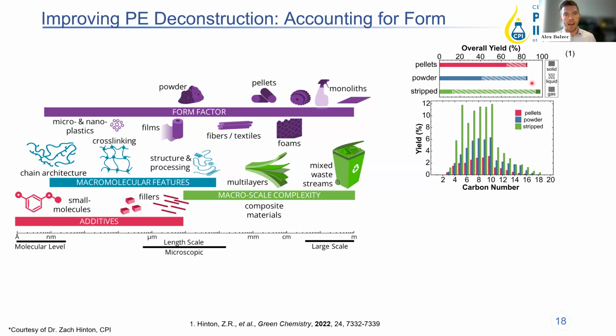And what we see is that the powder HDPE has a higher liquid yield for the same reaction time compared to the pellets. And that's because really in the pre-mixing step, we can get more catalyst to polymer interactions because of just the size distribution. And in the case of the strips, what we see is an even higher yield. But what I also want to point out is that the distribution of our liquid yields actually doesn't change significantly with the form factor. It's just you get a faster reaction. And so this is really back to the mass diffusion limited process. If you have really large plastics in shape and size, they're just going to react slower. It takes them longer to diffuse and reach the catalyst surface compared to something that can be ground up extremely small.